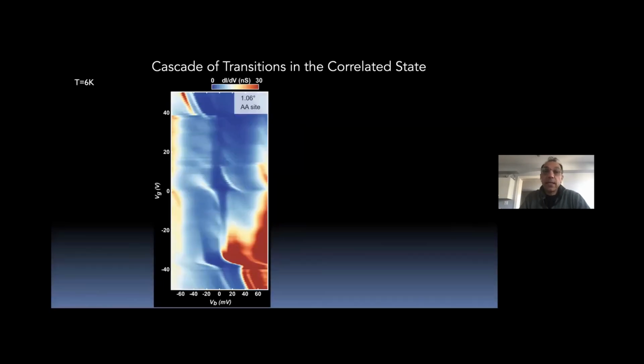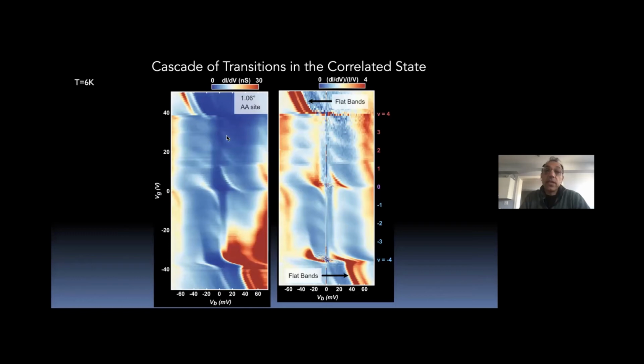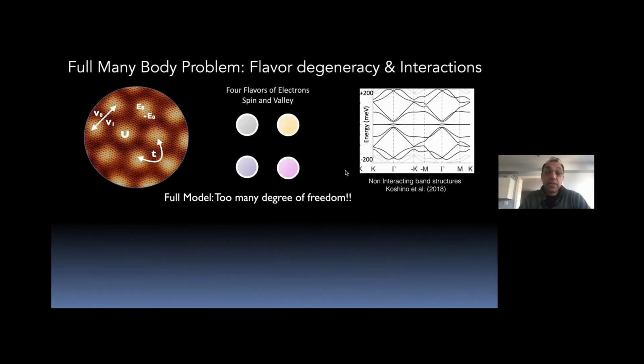To bring that out, we can take the dI/dV and divide it by I/V, which takes out the fact that your STM tip is actually moving up and down because of a set point when the tunneling current is changing dramatically. And what you can see here is this sharper feature comes out more clearly in the experimental results. So the system resets its property, and this relates to what Dimitri showed you, every quarter filling as you go through these integer fillings of the system. So this is again related to the strong correlation in this system.